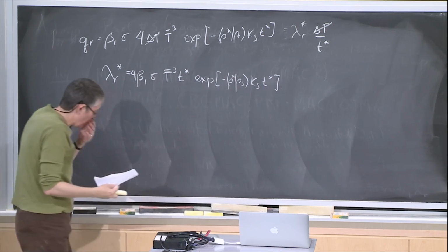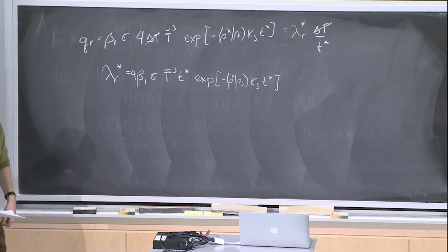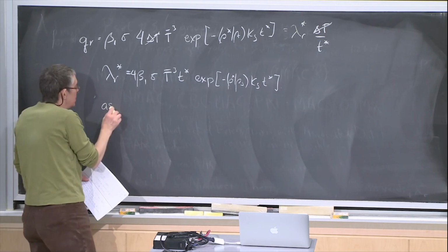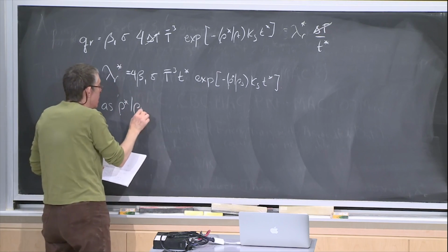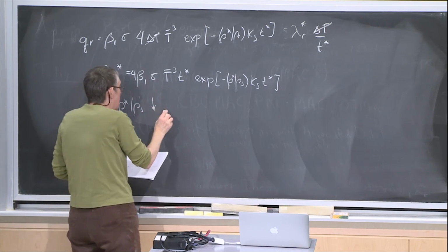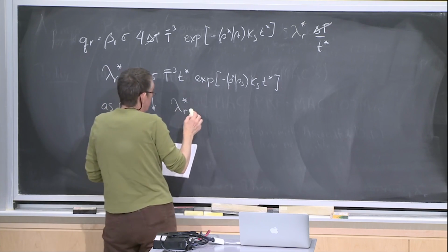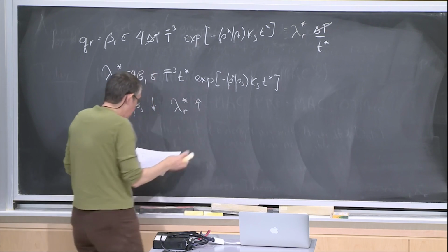And that's our thermal conductivity contribution from radiation. One of the things to notice here is that as the relative density goes down, the contribution from radiation to the thermal conductivity of the foam goes up.